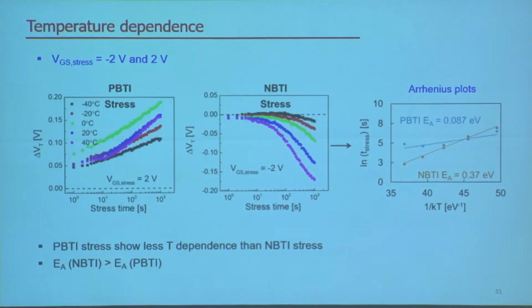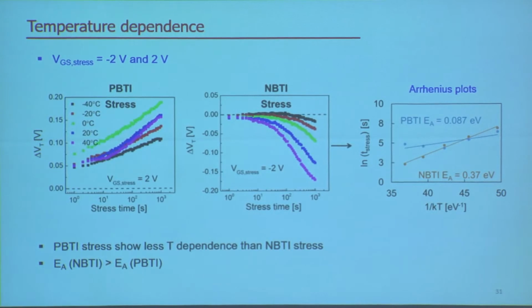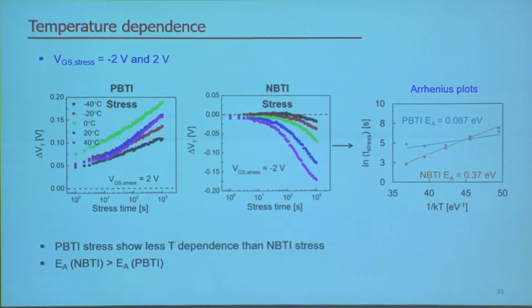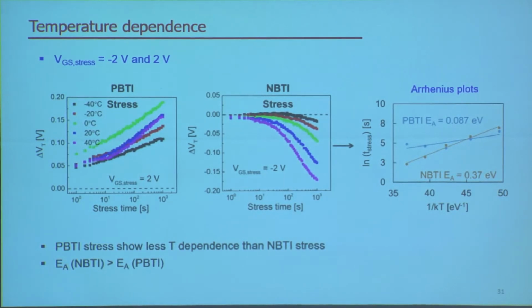We also look at the temperature dependence. In this set of experiments, we fix the stress voltage. So for PBTI, we stress the device at 2 volts, and for NBTI at -2 volts. And we repeat the same experiment at different temperatures from -40 degrees C to +40 degrees C. And again, we trace the stress time evolution of delta VT. And what you see here, you can probably see that for PBTI, there seems to be less of a temperature dependence compared with NBTI. And that is indeed the case if you look at the Arrhenius plots on the right-hand side. The activation energy of NBTI is about 0.37 electron volts, and it's only 0.087 electron volts for PBTI.